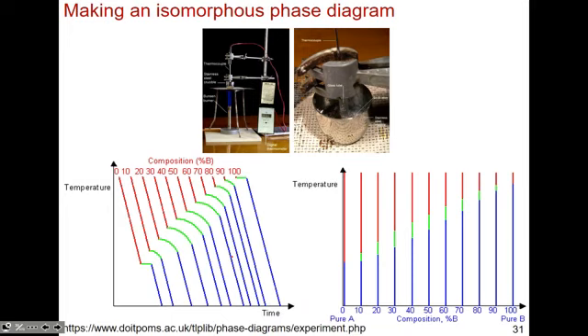Okay. And the way people measure this is pretty standard. You stick a thermometer in there and you weigh it out and you map out this phase diagram, which is great until your world becomes more complex. And then, as I mentioned, you can start culling a database of all these energetic parameters, all these temperature values, and then you could start to make your own binary phase diagram, just computationally. So you could see if you measure the temperature as a function of time, if you heat it up and then just let it cool with different composition, you could start to map out the phases.